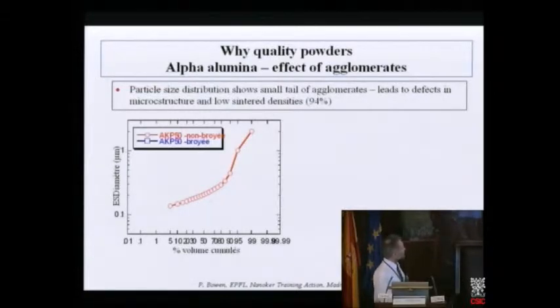So this is a plot on a log scale. This is a logarithm of the diameter. This is the cumulative distribution on a probability curve. If we have a straight line, then the distribution follows a log normal distribution, okay? And we can see it's relatively straight, and then at the end we have this tail of agglomerates, so up to about 300 nanometers, and then above 300 nanometers we lose the log normal distribution. We have a second mode in our distribution, and these are aggregates.